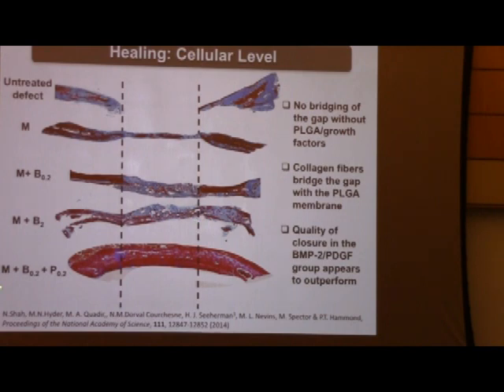However, if we introduce the BMP2 PDGF combination, where PDGF is on top, we see that we get bone that looks very much like the matrix itself on the edges, bone that looks like the native bone. We get a very nice vascularized system throughout the bone, and on top of that, we get this very nice smooth bone surface.